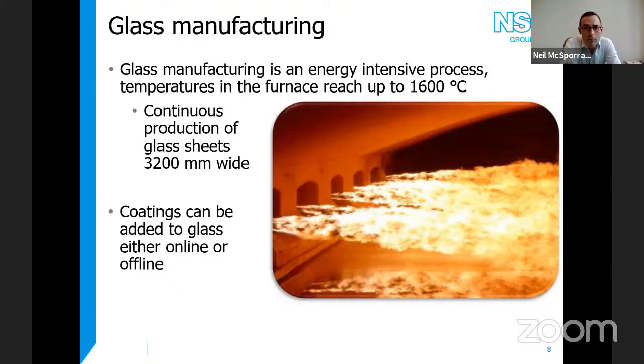The glass is used in many products, but we really add functionality to that glass to provide different impact, really, by using our coatings. And we use two types of coatings. One, which we term online, which is chemical vapor deposition during the glass manufacturing process, and the other offline, which is typically sputtering, or PVD. We also operate some wet chemistry coatings like sol gel, but again, I won't be speaking about those today. I'll focus in on CVD and PVD.